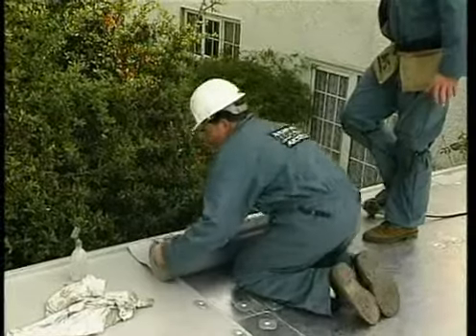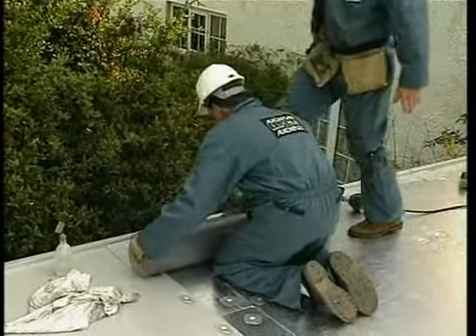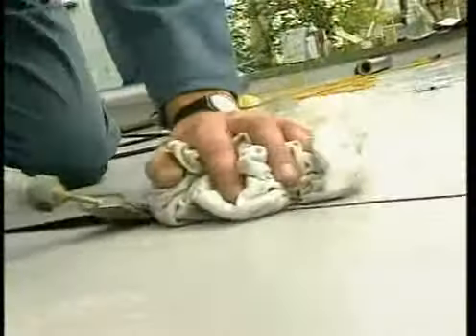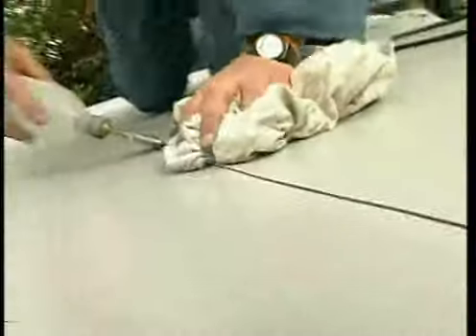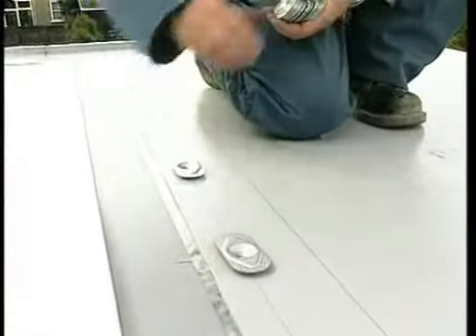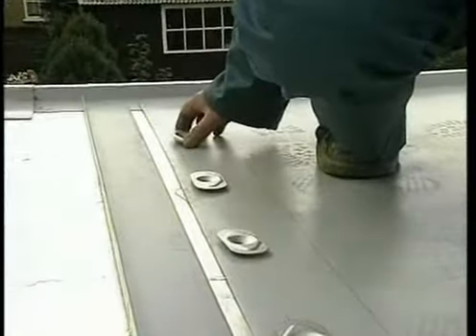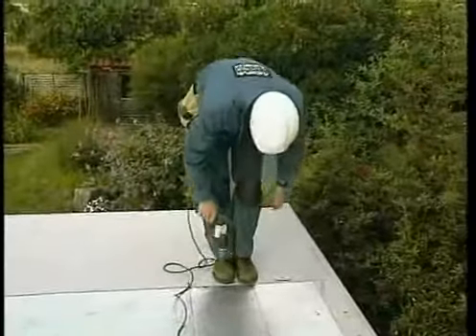When mechanically fastened systems are laid over metal deck substrates, the rolls of membrane are laid at 90 degrees to the deck direction. Where the substrate is continuous, for example a timber deck, the direction of the roof sheets is not critical. It's quite common for sheet overlaps to face the flow of water, as the laps are not glued but homogeneously welded together to produce an impervious seam. The edge of the roofing sheet is marked with two parallel lines. The first, 30 mm from the edge, is the center line for the fixing plates and screws.